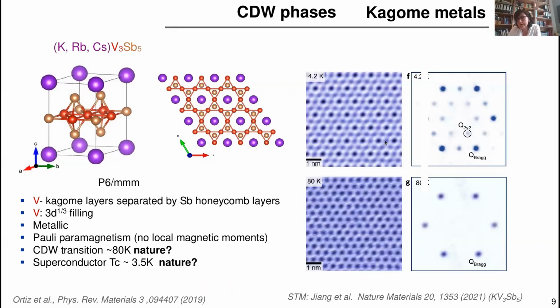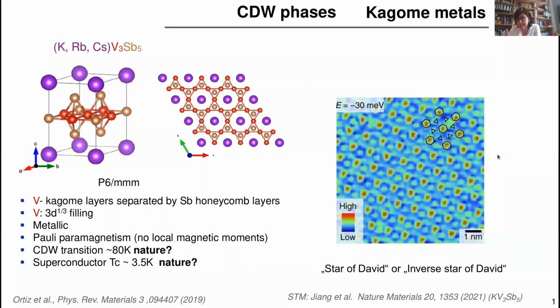So now, however, when going down in temperature, the system undergoes this charge density wave transition, and there are extra peaks that one can observe, corresponding to a 2x2 charge density wave. So there is a doubling of the unit cell. And moreover, what kind of charge density wave has been observed?